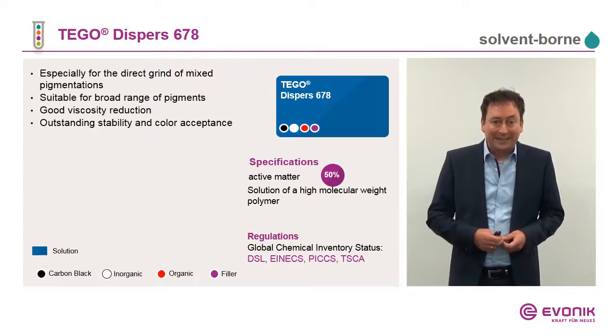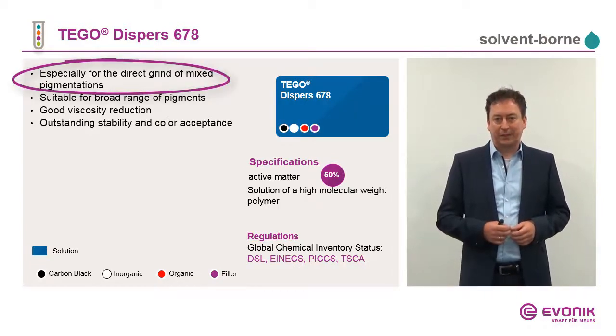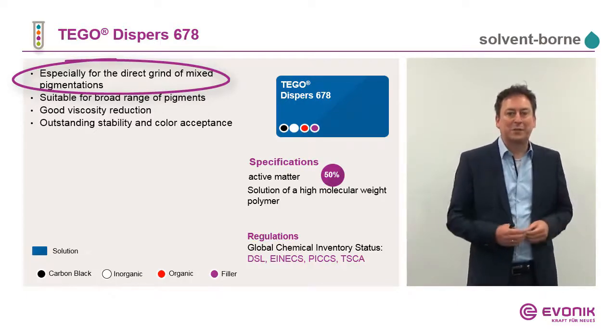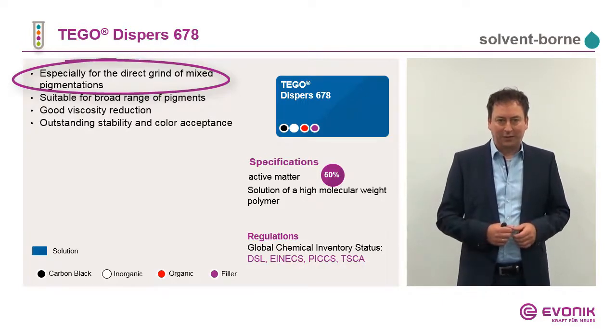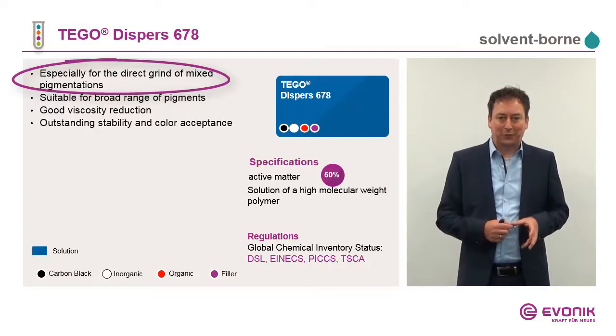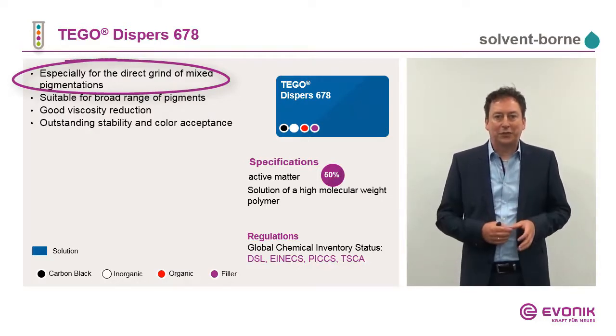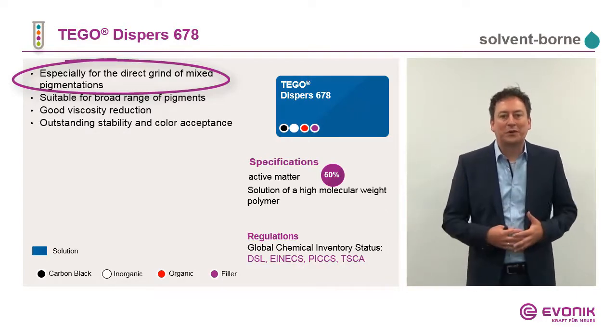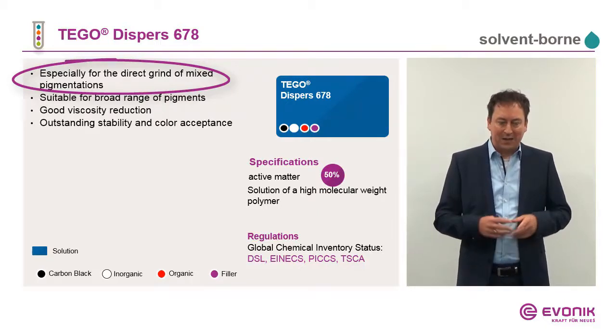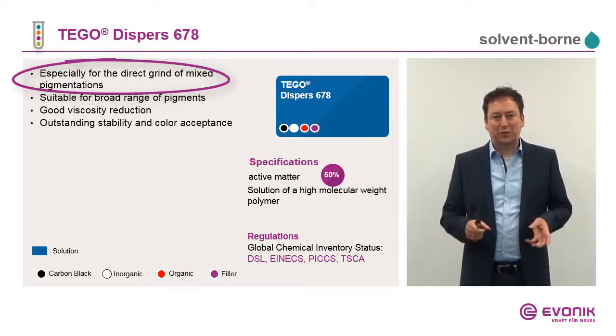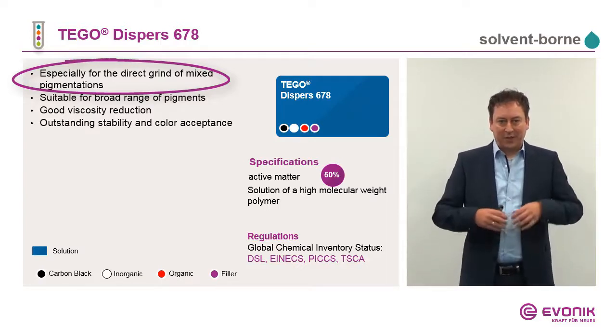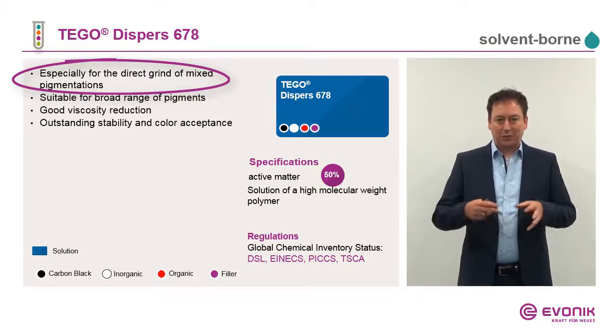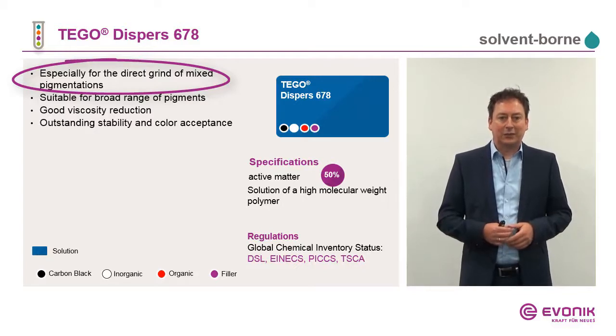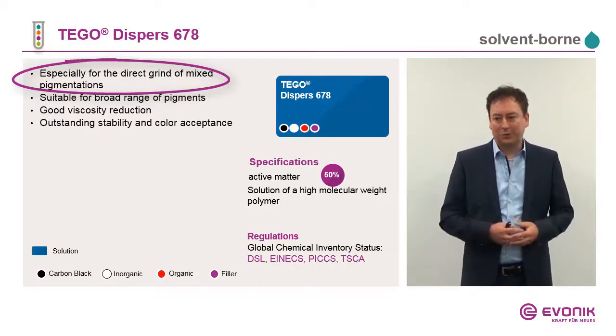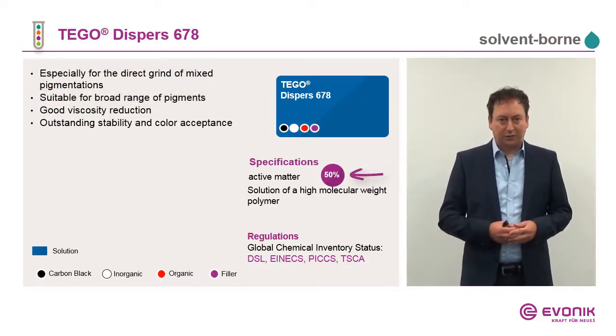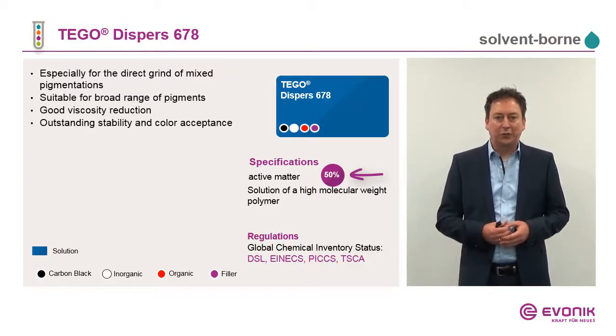The TEGO Dispers 678 now, it was developed for mixed pigmentations. So when you use a lot of different pigment types in the direct grind, then you usually see a very high dropout value, so a very high delta E. And because the additive that you use usually is a specialist for one pigment surface. The 678 now does not care about the pigment surface, so it is very good for all kinds of pigments and will develop the color strength of all pigments the same. And so you do not see a very high delta E. So the direct grind, the rub out is very good. It is 50% solid, but still also okay for low VOC coatings.